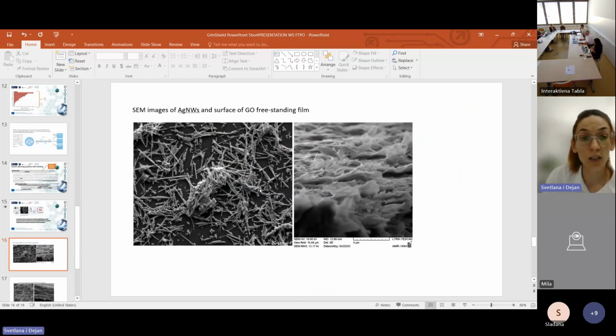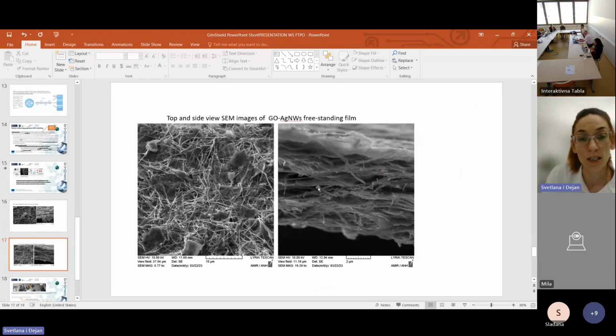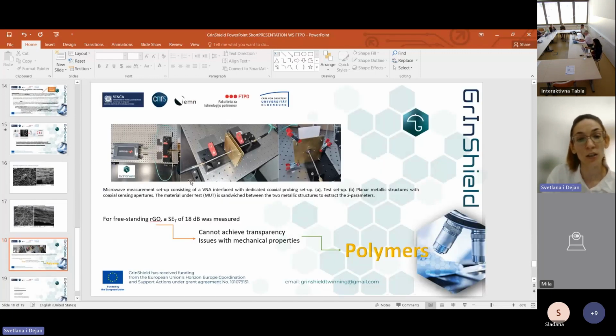So far, we have produced single silver nanowires, graphene sheets, and the composite. These are SEM images of these materials. We produced these materials in freestanding form, measured shielding efficiency, and obtained a result of 18 decibels, which is close to the targeted value. But the issue here is with the freestanding